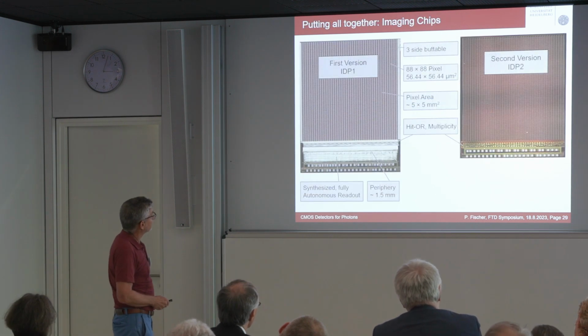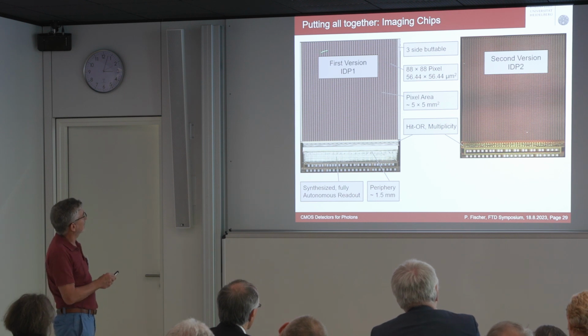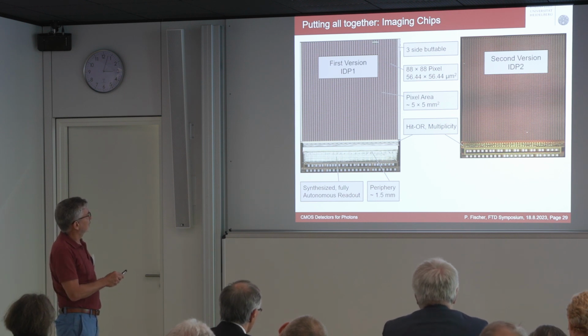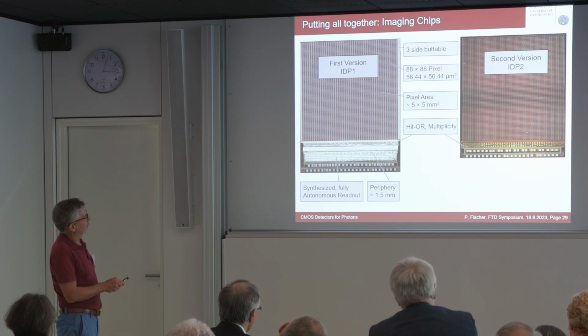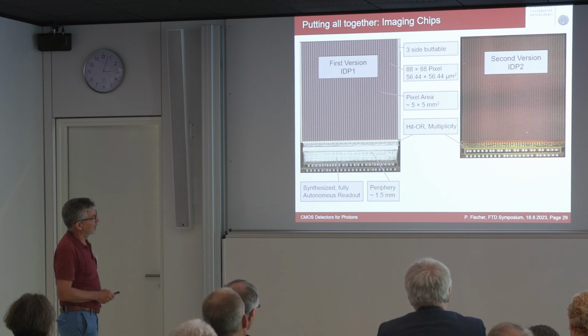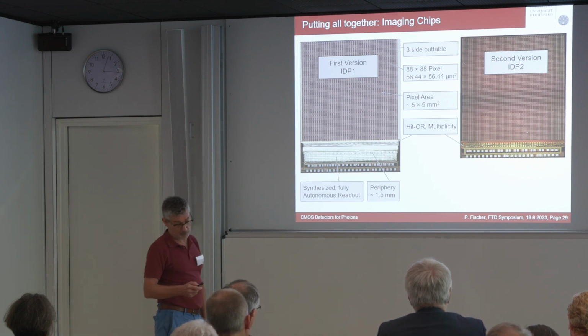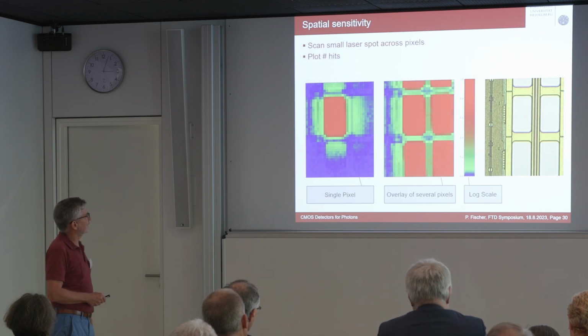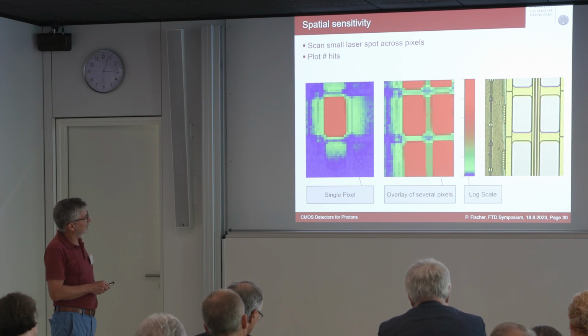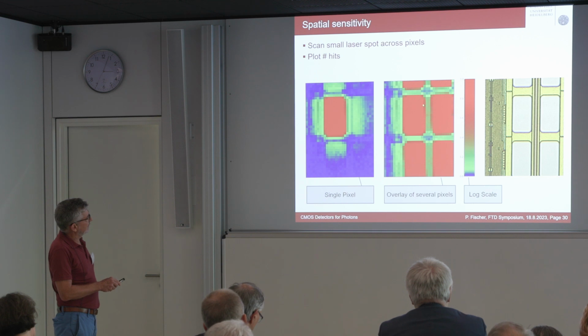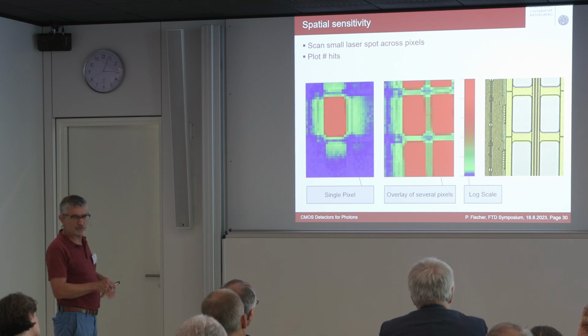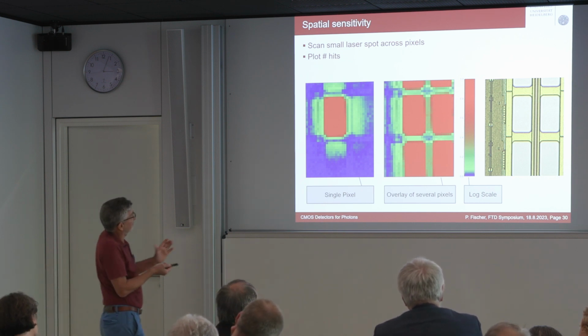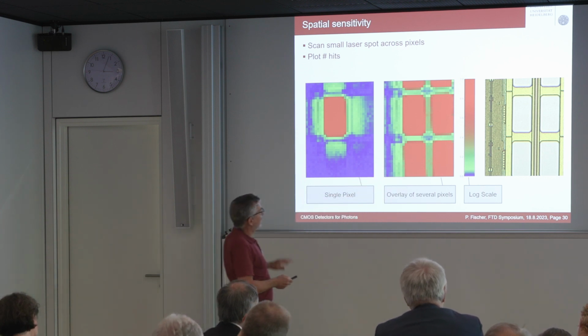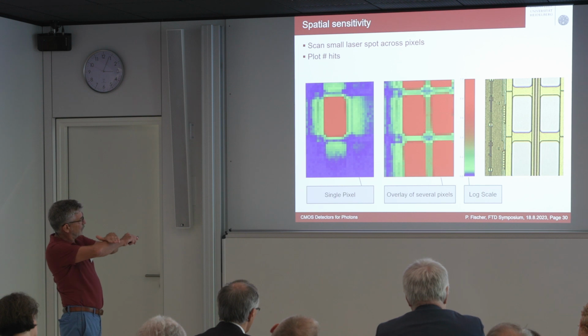And this works. So we have made several chip versions of this. These are 2-dimensional imaging chips, which can see the single photons in these pixels. We have on the order of 100 by 100 pixels of roughly 50 by 50 square micron with a fill factor of roughly 50%. If you scan a laser spot across this detector and you measure how often you respond, we were really pleased to see that we exactly find the sensitivity which corresponds to the area. So these spots don't have inactive edges. You could maybe find that they are only really sensitive in the middle. And this is persistent for all the chips we have. The response is really nicely flat.